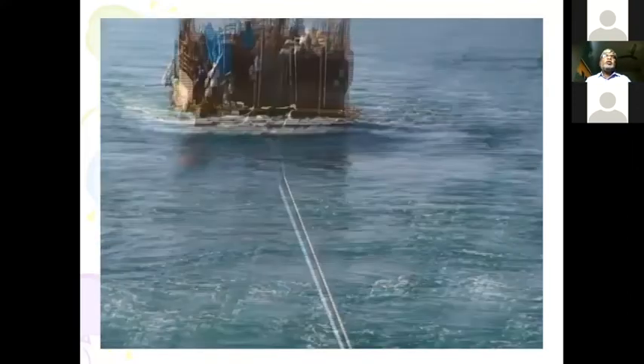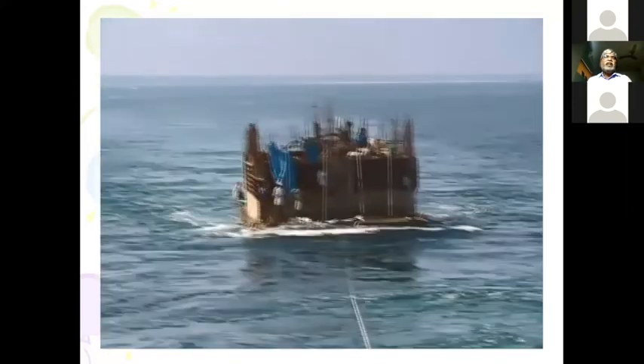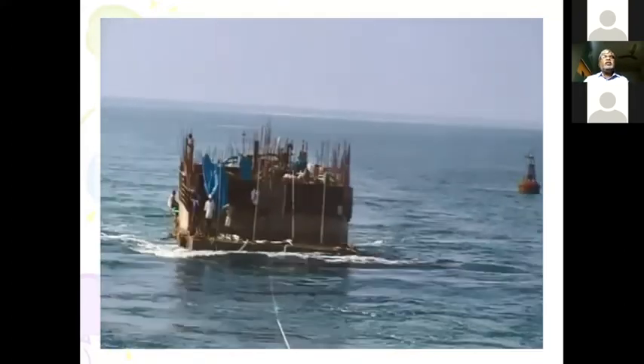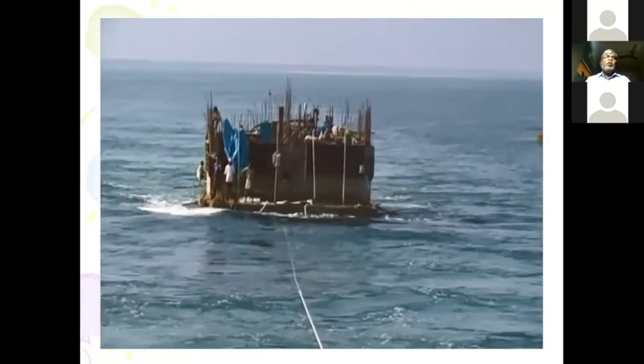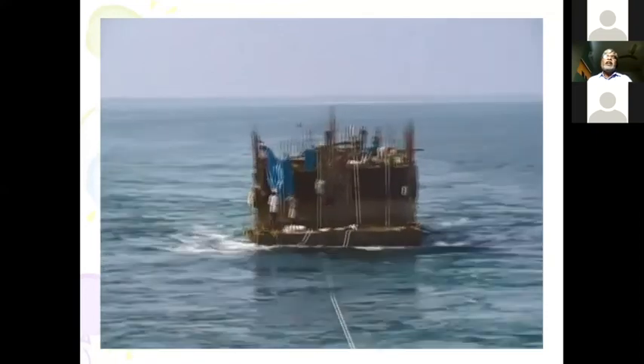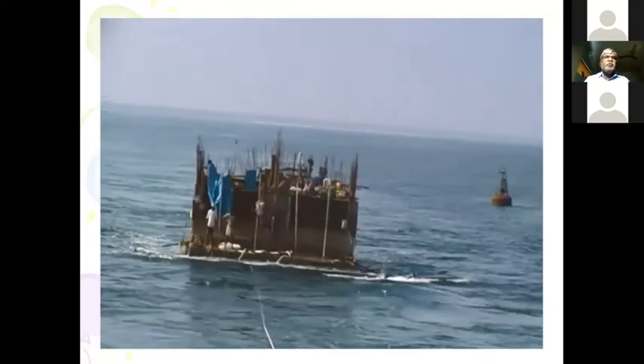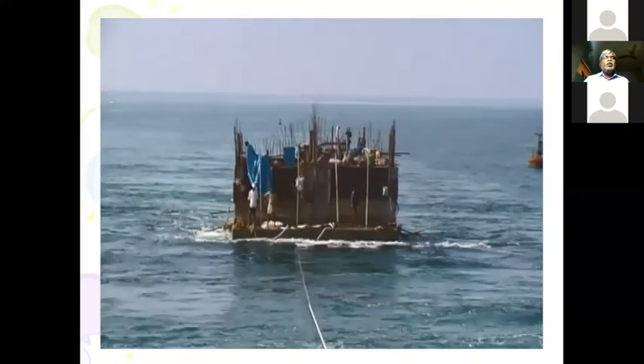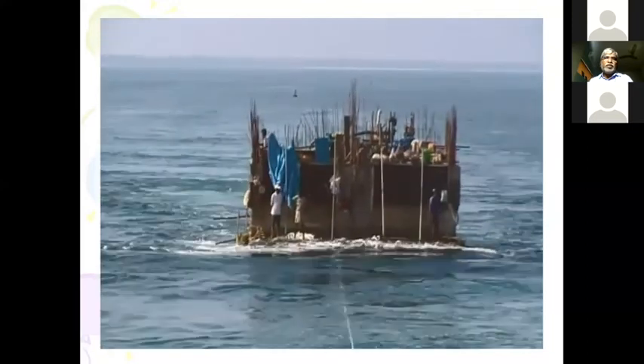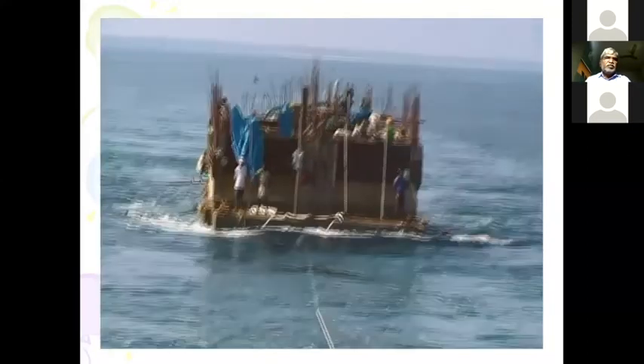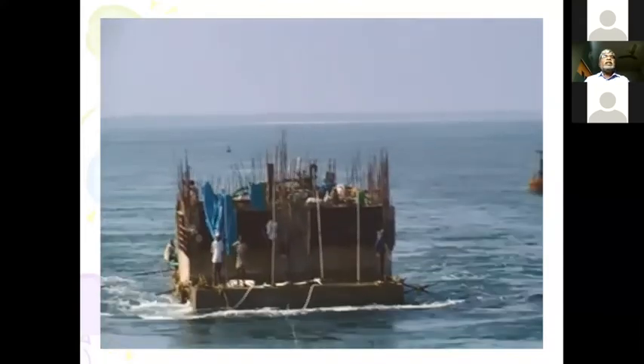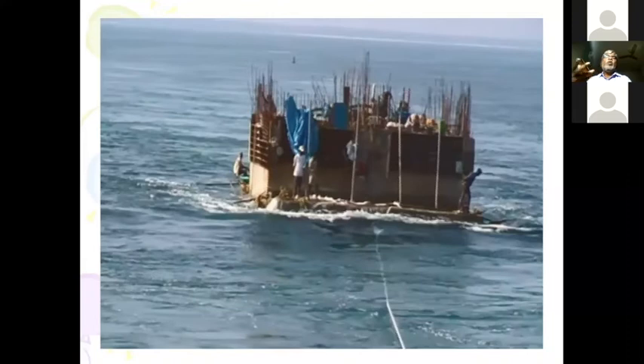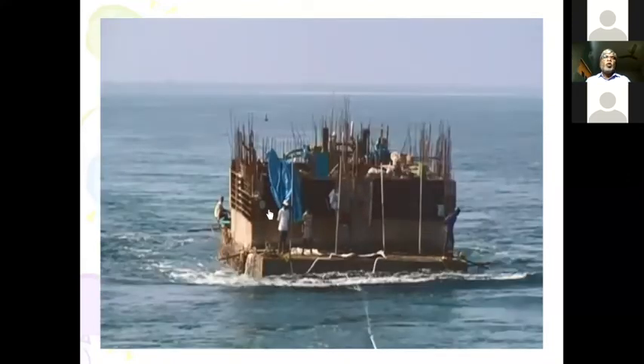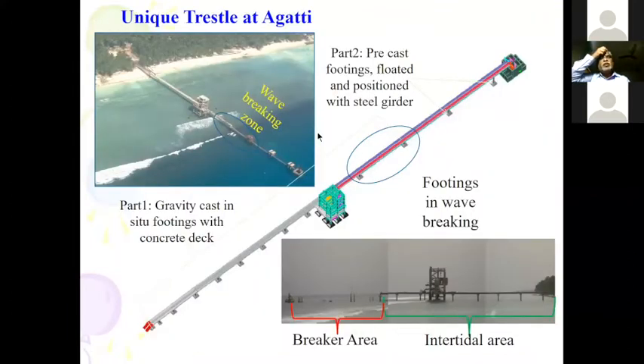The challenge over here is the cold joint. We don't want any cold joint leaking to take place, so we have used both type A and type B waterproofing systems, because with type A alone we will not be able to go as per BS 8102:2009. We use these water stoppers, both PVC and expandable swellable water stoppers, and we have used admixtures where we have about 6 hours slump retention, and we avoided to the best possible extent any cold joint, so that it doesn't leak. So this was floated and then brought to the particular place where it is supposed to be anchored, and the anchoring was over as we discussed.